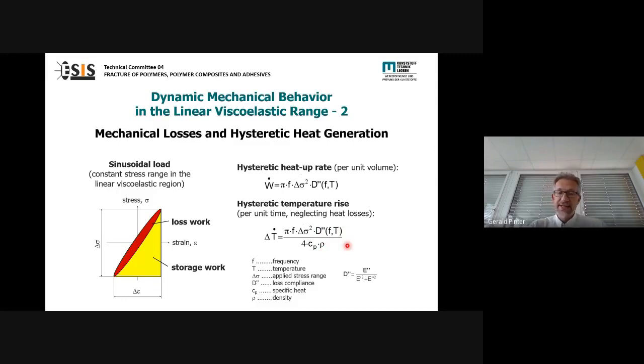loss compliance. So then the loss compliance typically is very high in the region of the glass transition temperature of the polymers. So you have to be very careful if you are testing polymers in fatigue, if you are testing at a temperature that is around the glass transition temperature. There you typically have a lot of hysteretic heat up in the material.